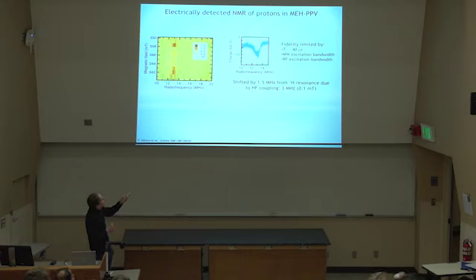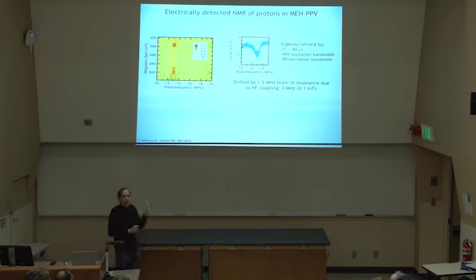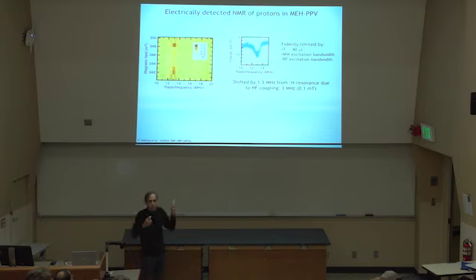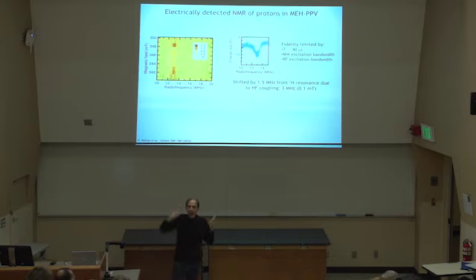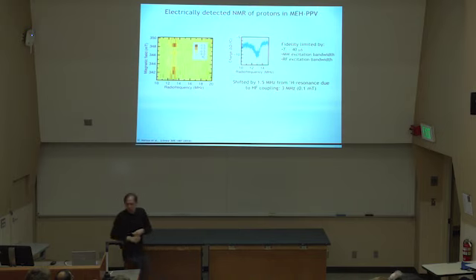Why is this so wide here? Well, that's the distribution essentially. Why do we have a resonance that peaks at about 13 megahertz? Well, that corresponds to our applied magnetic field. But why is it so wide? Basically, the width of that resonance is on the order of the frequency where it resonates. That is because this distribution reflects all the individual hyperfine interactions that hydrogen has with nearby charge carrier states, these polaronic states of electrons and holes in this material.